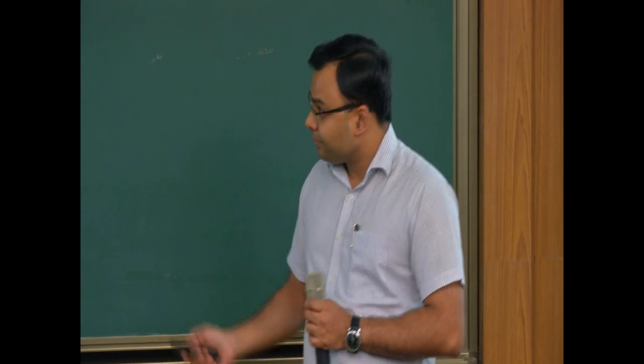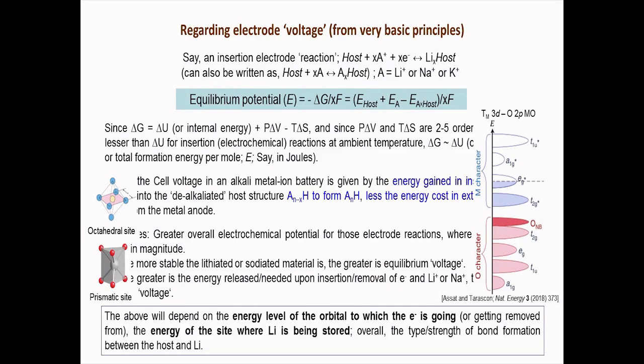In other words, if the lithiated host is more stable compared to the unlithiated host, then of course the energy E goes down, and so the difference between these two goes up, and accordingly one gets a greater equilibrium potential. In terms of thermodynamics, that is exactly what governs the equilibrium voltage of lithium storage, sodium storage or potassium storage in any material electrochemically. So the inference is that if the lithiated or sodiated material is more stable as compared to the unlithiated or unsodiated host, then it will lead to a greater voltage.